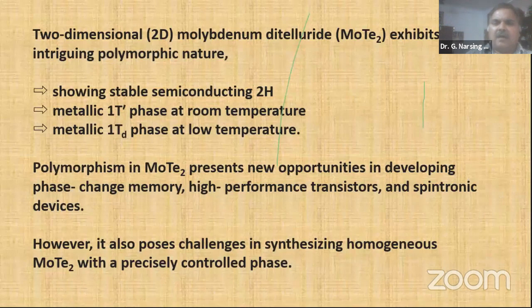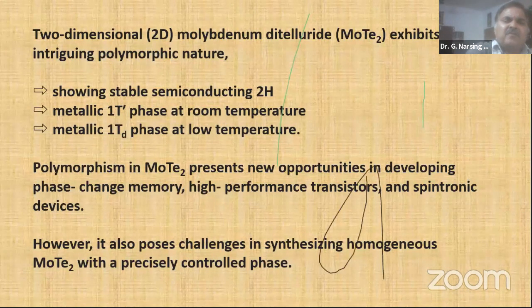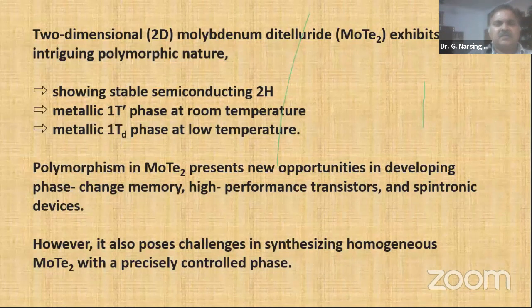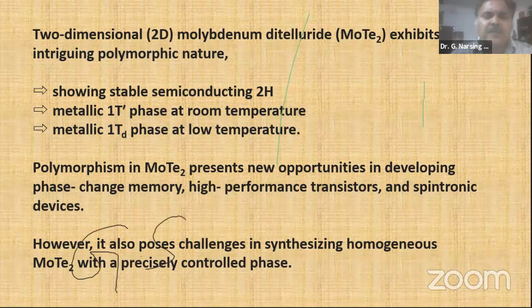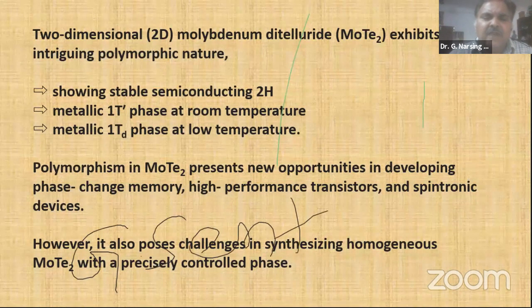It depends on your preparation method or preparation condition. There is a phase transition from 1T prime to 1Td at around 245 K, so there is a possibility of a phase change material. That's why this polymorphism presents a new opportunity in developing phase change memory, high performance transistors, and spintronic devices. However, it also poses challenges in synthesizing homogeneous material, that means in a single phase, precisely controlled, which is very, very difficult.